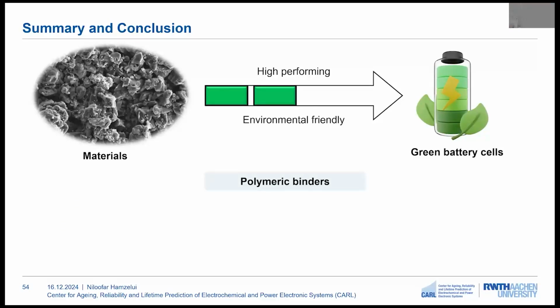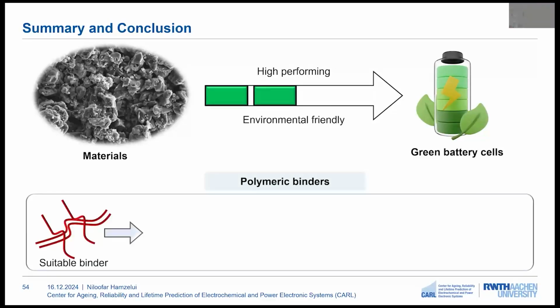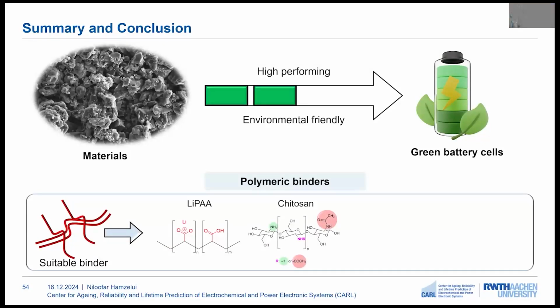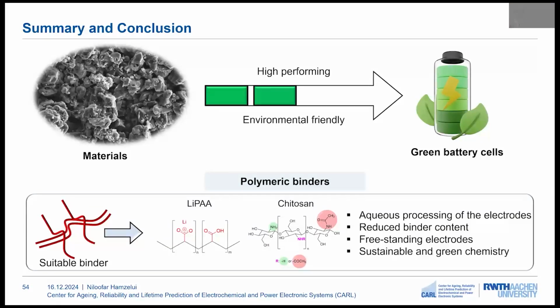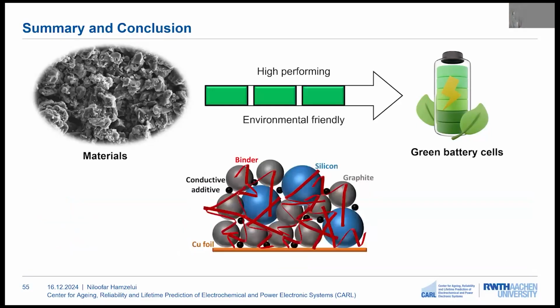In the second part, polymeric binders were investigated, such as LiPAA, or natural polymeric binders such as chitosan, which results in a more aqueous processing of the electrode, and we could reduce the binder content in this electrode and produce freestanding and sustainable chemistries on the anode side. So by combining these binders and the optimized silicon to graphite ratio, we can produce more green and environmentally friendly negative electrodes in batteries.